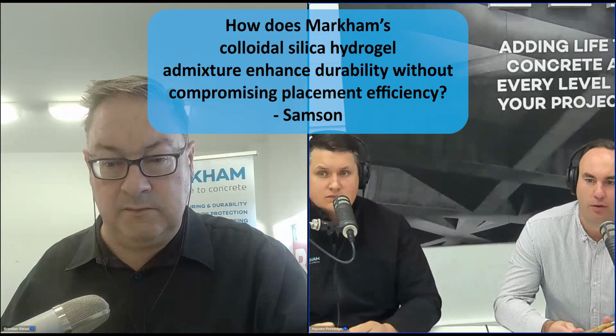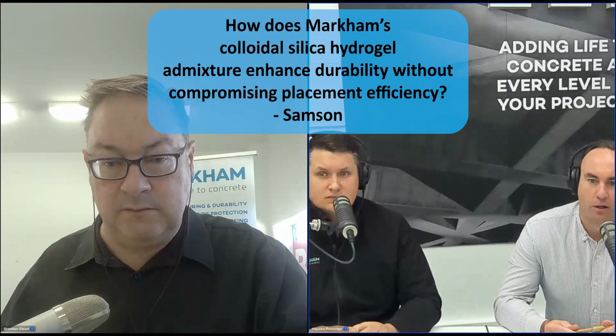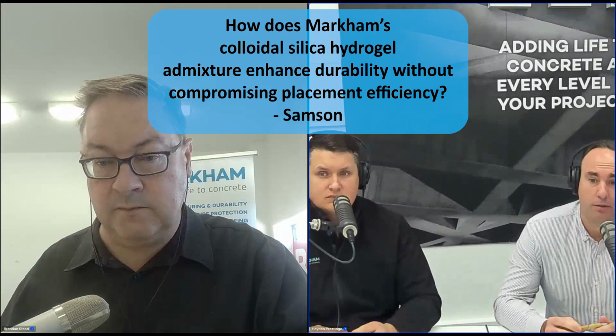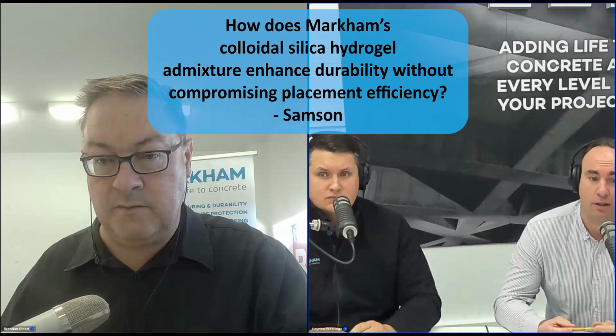So, a question there around how does the colloidal silica hydrogel enhance durability? Probably touches on roughly what I was just saying, as the hydrogel essentially sets up in the porosity and blocks the porosity to stop moisture migration, as it grows more calcium silicate hydrate and really densifies that concrete matrix and protects it against contaminants, acids, chlorides, those sort of things that get into the concrete.